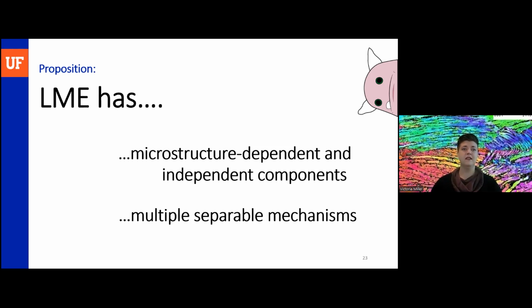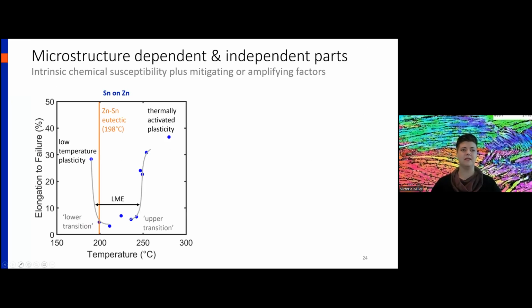So first, microstructure dependent and independent parts. Looking here, this is molten tin on zinc, and this is temperature versus elongation to failure. Here, we get a lot of elongation to failure at low temperatures. We get low temperature plasticity. When we increase the temperature somewhat to about 200 C, we get embrittling behavior. Note that this happens right near the zinc tin eutectic temperature.